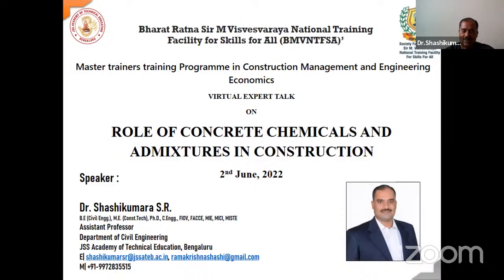See, these are all the advisable areas where we can use this self-curing compound. Even BMRCL, all the RC elements and deck slab elements. If you see the tunnel element, I personally visited on previous visits. Within 8 hours, they are able to produce tunnel lining elements. There are 3 shifts. The tunnel elements of 6 to 7 elements, including the key element, they are able to produce 50 megapascal in 8 hours.